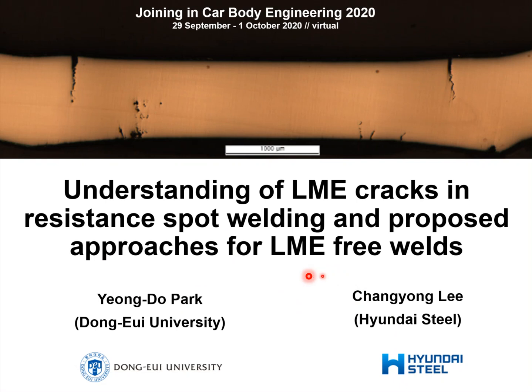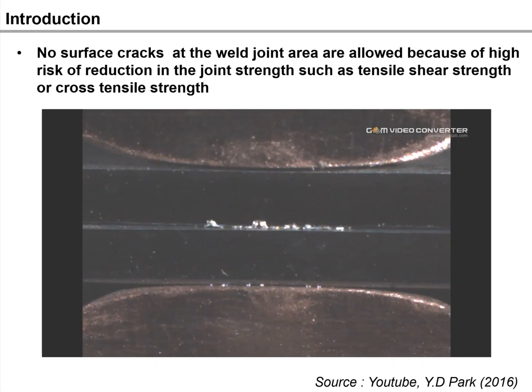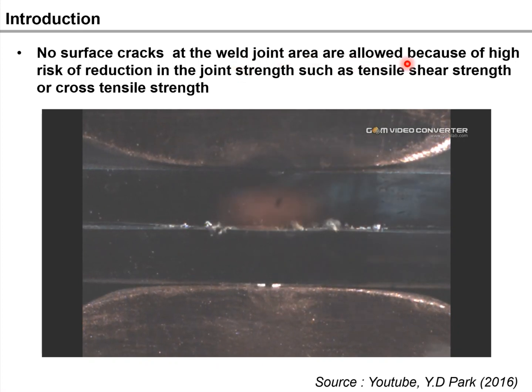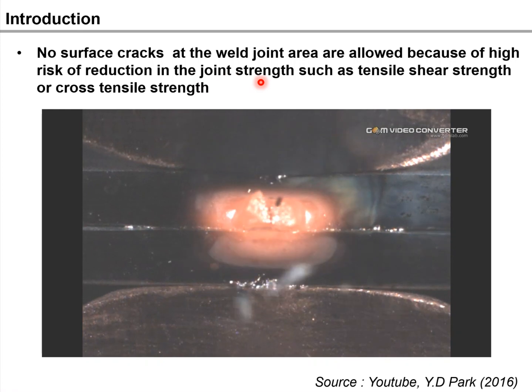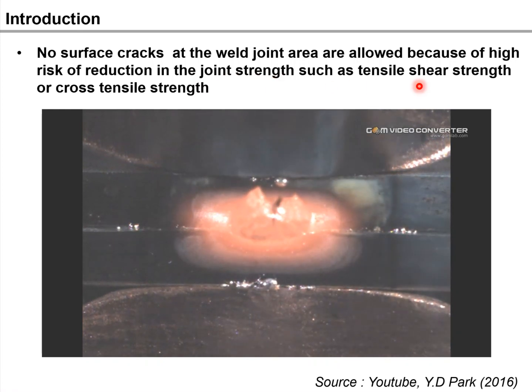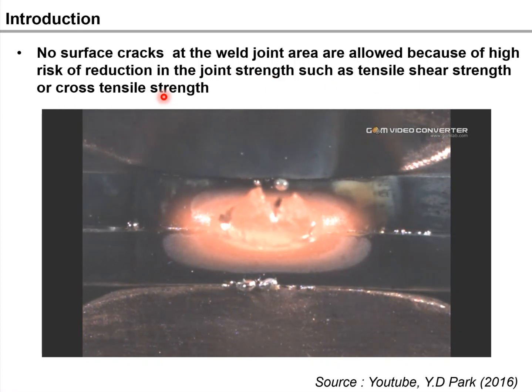My speech today addresses the understanding of LME cracks in resistance spot welding and proposed approaches for liquid metal embrittlement-free welds. No surface cracks at the weld joint area are allowed because of the high risk of reduction in the joint strengths, such as tensile shear strength or cross-tensile strength.